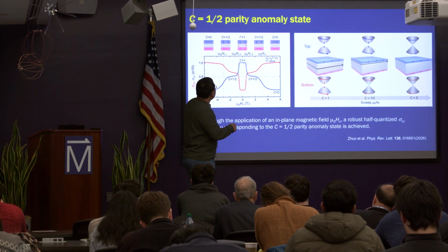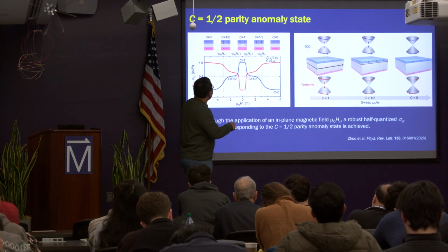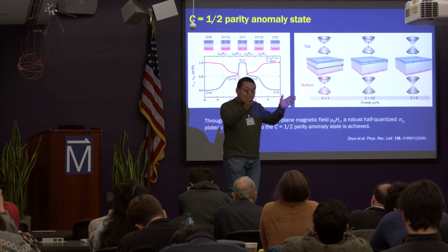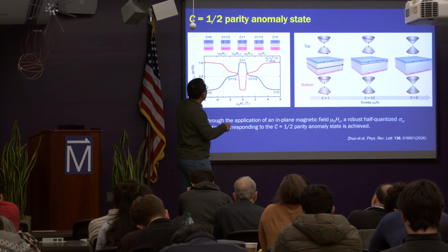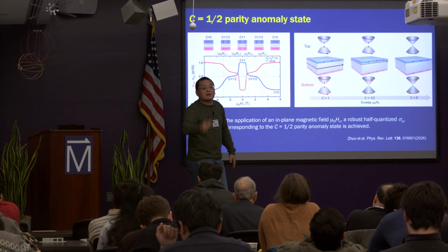For vanadium the Hc is around 1 Tesla, and for chromium it is around 0.1 Tesla. So when we apply an in-plane magnetic field, chromium will become in-plane, but vanadium still keeps out-of-plane.